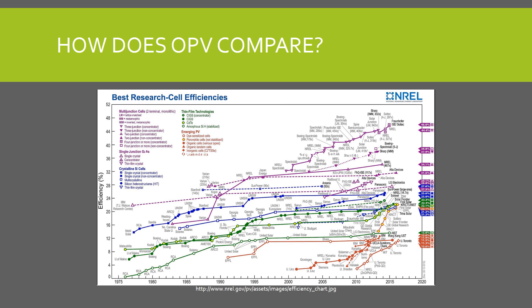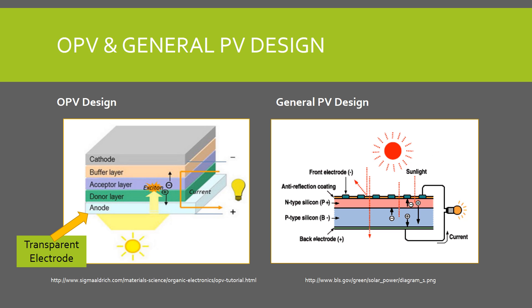As you can see, OPV have efficiencies near 11%, while other technologies have efficiencies between 20 and 40%. The main difference between the types of cells is that OPV does not make use of semiconductor PN junctions. Rather, organic cells have a heterojunction, with an electron donating and an electron accepting material, sandwiched between two electrodes. Because these materials aren't crystalline, they don't have a conduction and a valence band, and carriers move by hopping between localized states. This is why carrier mobilities are low compared to inorganic semiconductors, and OPV cells have to be thin, which renders them less durable.